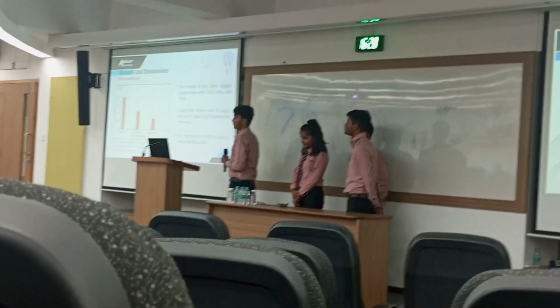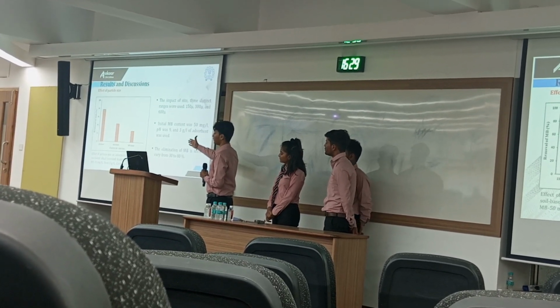Thank you, Pradeep. Now I want to discuss some factors affecting the experiment. First one, the effect of particle size. In order to study the impact, three distinct particle sizes, 150 micron, 300 micron, and 600 micron, were used, where the initial methylene blue concentration was 50 mg per liter, at 3 gram per liter of adsorbent. From the results, we can see the 150 micron particle size has the greatest efficiency of more than 80%, while 300 micron and 600 micron have 55% and 30% efficiency respectively. This is because the smaller size particles have a much more effective surface area than the larger size particles. The next one, the